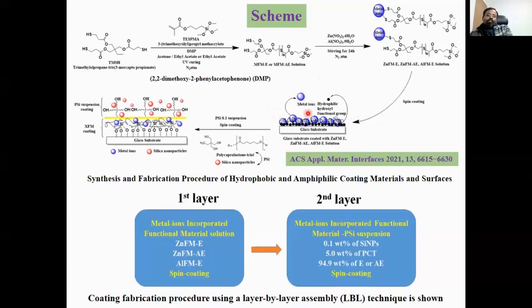and further we modify this hydrophobic to highly hydrophilic, because as I introduced the topic, anti-fogging as well as antibacterial applications. So in this case we plan to make two types of substrate, hydrophobic substrate as well as hydrophilic substrate. First we made the hydrophobic substrate, and then modified it to highly hydrophilic using some hydrophilic materials like polycaprolactone as well as silicon nanoparticles.